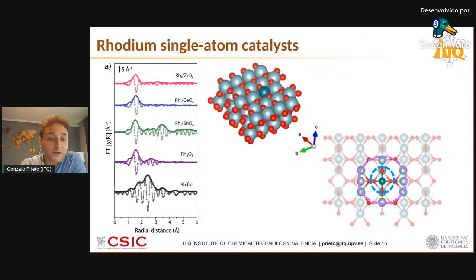This is the case, for instance, of X-ray absorption spectroscopy, which is commonly used as a technique to investigate atomicity for this type of supported metal catalysts. What one would typically look at is the Fourier transform of the EXAFS region of the spectrum, compared to some reference materials. In this case, I'm showing metallic rhodium and bulk rhodium oxide both at the bottom and then different single atom catalysts on the top. And then one could just look at the absence of modulus signals at radial distances beyond the first coordination shell, which in this case would be rhodium to oxygen. That's the peak showing at around 1.6 angstroms, phase uncorrected distance. And if there are no further features, one would say, okay, there are no additional rhodium atoms in second or further distance coordination shells.